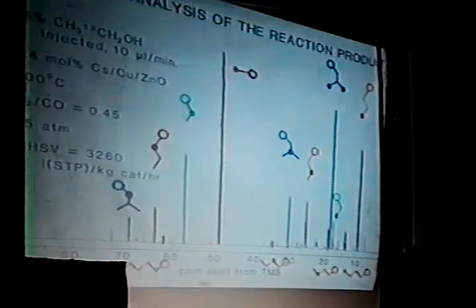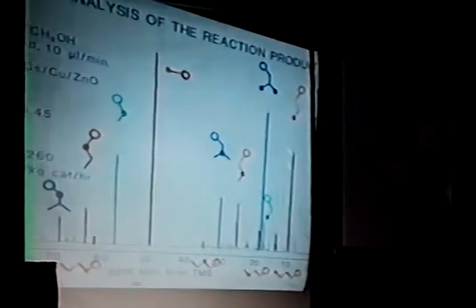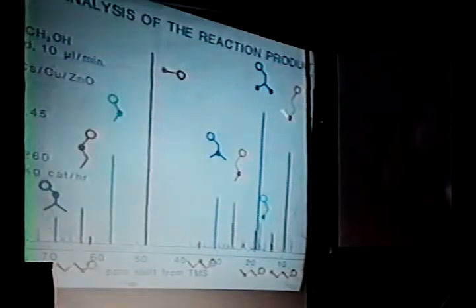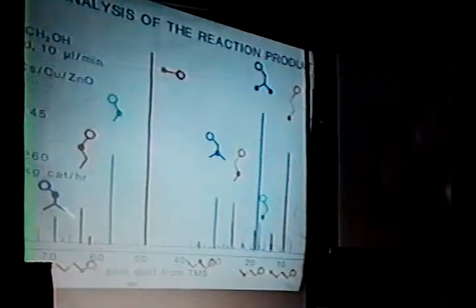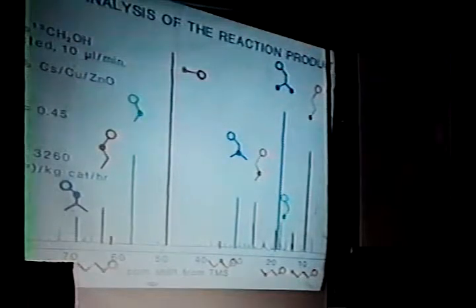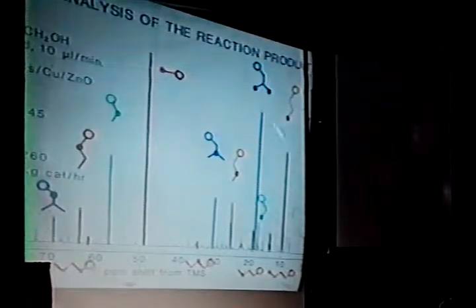The subsequent product, linear propanol that one gets, has a major portion of the label on the outer carbon, not in the inner carbon, not in the middle carbon, but on the outer carbon, whereas the middle carbon and the inner carbon are low. What this means is the following. The C1 intermediate, which we believe to be an aldehyde, adds itself on the beta carbon of ethanol and forms an oxygenated end here, and then this oxygen is kicked out by a mechanism which we call reverse aldol synthesis with oxygen retention on the C1 intermediate. If we retain the C1 oxygen on the C1 intermediate, we get that oxygen here. This is the C1 intermediate, and this is the turnaround ethanol, and the reaction is quite selective to this.